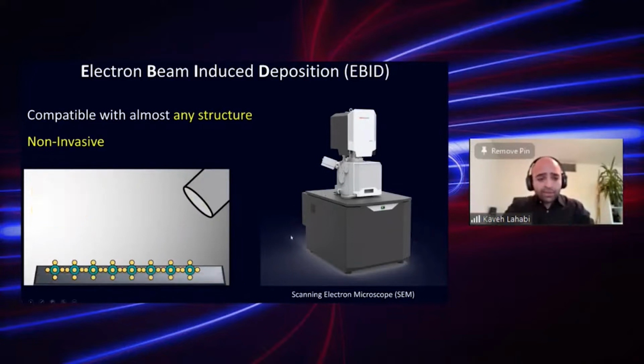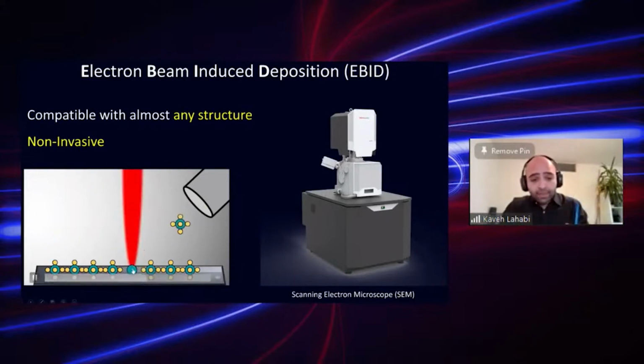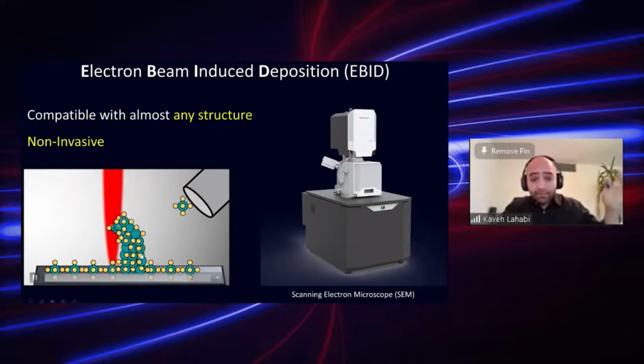Now, these molecules are stable until you expose them locally to a focused electron beam, at which point they dissociate and form a deposit. In our case, that would be tungsten carbide. And of course, if you go out of plane and you scan the beam carefully, you can even make 3D structures with this.